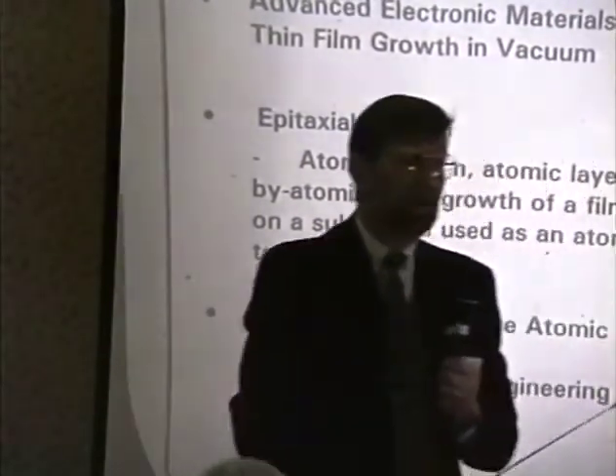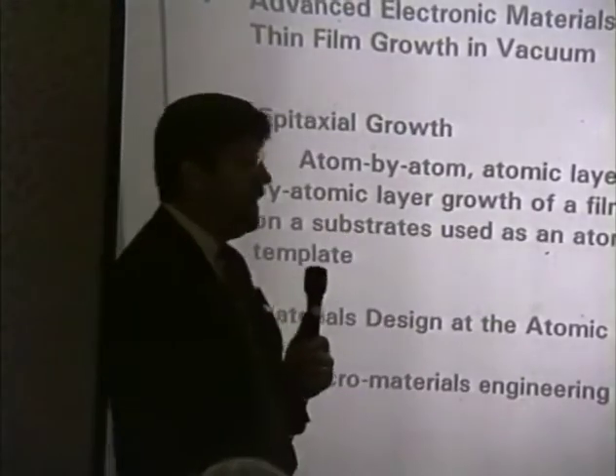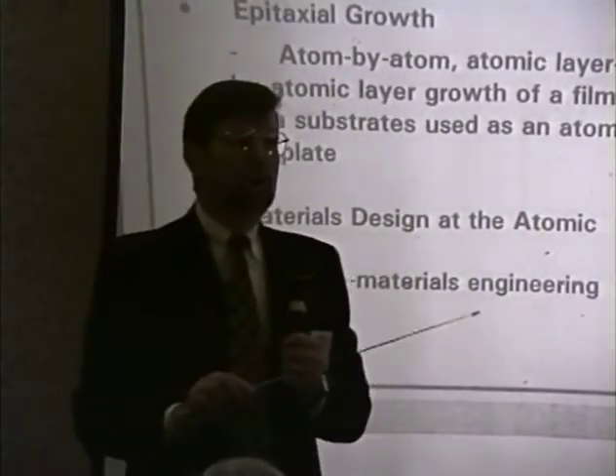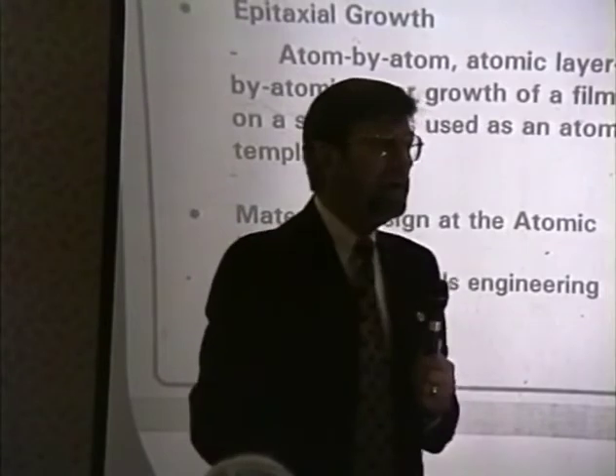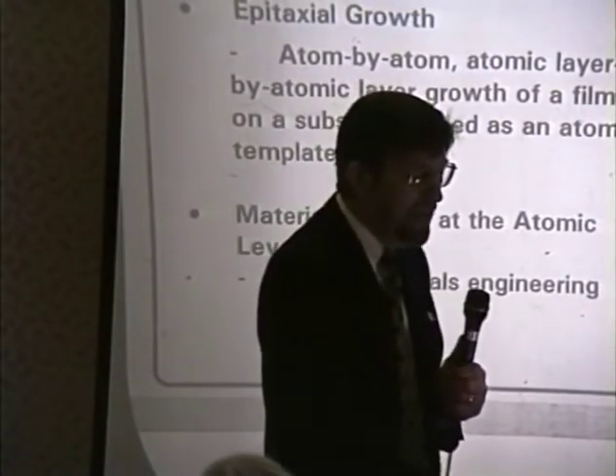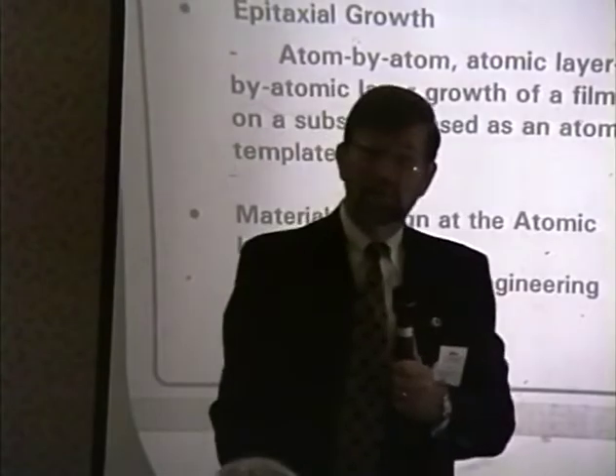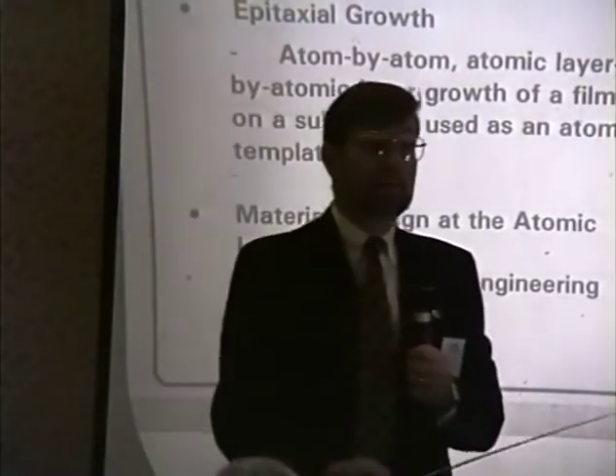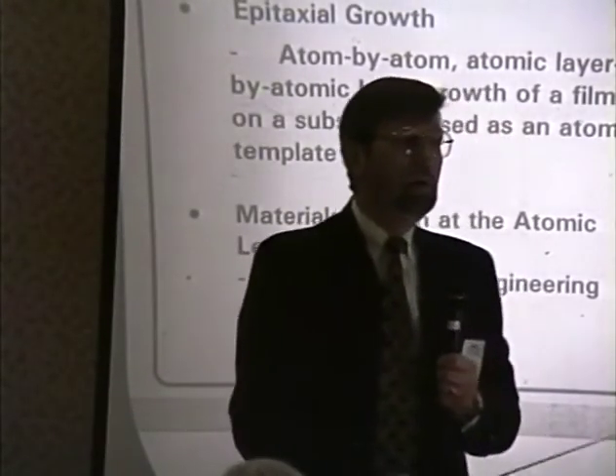And we do that through something called epitaxial growth. Epitaxial growth is a technique of making thin films that was developed in the late 70s, early 80s at Bell Telephone Laboratories by Al Cho and John Arthur. And it really is a growing of a thin film material one atom at a time, one atomic layer at a time. And if we look at the little schematic on the side, there are two sources of atoms that are being, say, evaporated or deposited on the surface, and they are alighting on a surface that has an atomic template there already, and they form a thin film, an atomically ordered thin film. And if this is done in a vacuum environment where there are no impurity atoms present, no other atoms present, then the thin film that you form is, in fact, an ultra-high purity thin film, atomically structured.